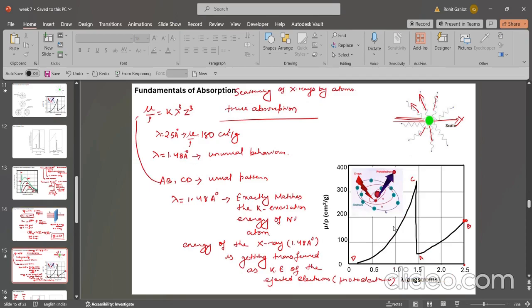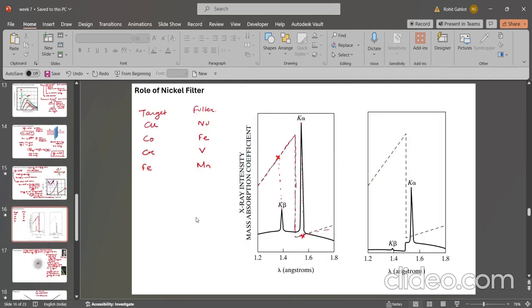Then if you move further to the fundamentals of absorption and scattering of X-rays by atoms. Suppose lambda is around 2.5 angstrom, then mu by rho is around 180 cm squared per gram. For lambda around 1.48 there is unusual behavior. This is the plot between mu by rho and lambda. AB and CD are the usual pattern, and at lambda around 1.48 unusual behavior is there. Lambda around 1.48 exactly matches the K shell excitation energy of the nickel atom. Then the energy of the X-ray at 1.48 angstrom is transferred as kinetic energy of the ejected electrons.